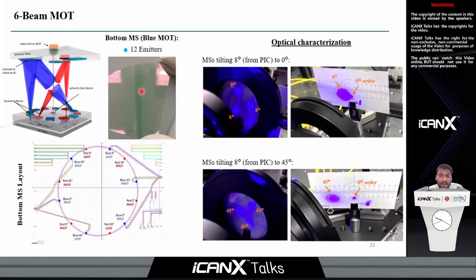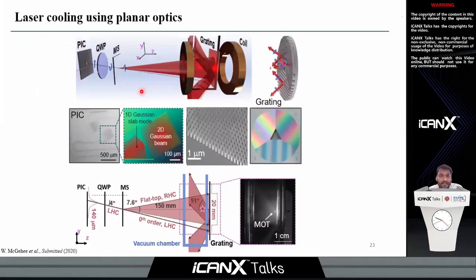Another quick example, this is my last slide, shows that if I have a PIC, then I can use this PIC plus metasurface approach to trap atoms in a completely planar configuration. This work was spearheaded by William McGehee when he was here at NIST, where he showed quite elegantly that if I put these things together and use this grating MOT approach, then one can trap atoms with performance that is better than, say, one would get from a Gaussian beam, because of the ability of metasurfaces to create circularly polarized flat top beams.